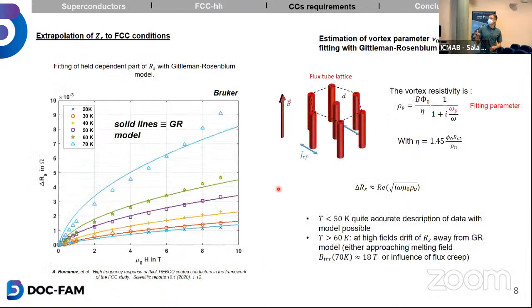So, as I mentioned, we determined surface vortex motion parameters, so the pinning frequency, the viscous drag of the vortex motion, also the Labusch parameter, which tells us how the superconductor behaves under a radio frequency magnetic field excitation. Okay, we measured it only at one specific frequency, at 8 gigahertz, and only up to 9 Tesla, but we can estimate some errors on these values, and with this I think we can more or less confidently estimate what surface impedance you would expect at other conditions, which are still in the regime of the model that we are using. Of course, it's a single vortex motion regime.